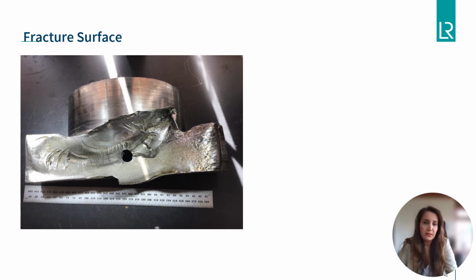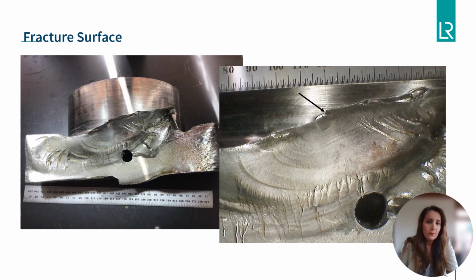It is clear that failure of the crankshaft had initiated from the main bearing journal with crack propagation predominantly through the crank web. You can see the fracture surface is generally flat with evidence of a single start mark located at the main bearing journal surface. Beach marks were also observed across the fracture surface, which emanated from a single start mark. You can also see river lines in areas of the fracture surface. These features are indicative of a fatigue failure mechanism which occurs upon application of cyclic loading.